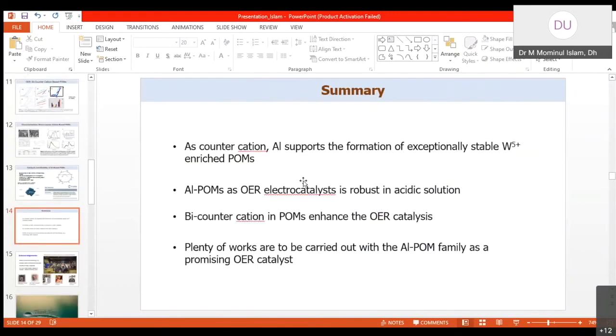So I am now summarizing this: as a counter cation, aluminum supports the formation of an exceptionally stable tungsten 5 state in this polyoxymetalate. Aluminum polyoxymetalate, as an OER catalyst, is robust in acidic solution, and counter cations, for example aluminum and chromium in polyoxymetalate, enhance the OER catalysis. Plenty of work is to be carried out with this new family of aluminum-based polyoxymetalate as a promising catalyst.